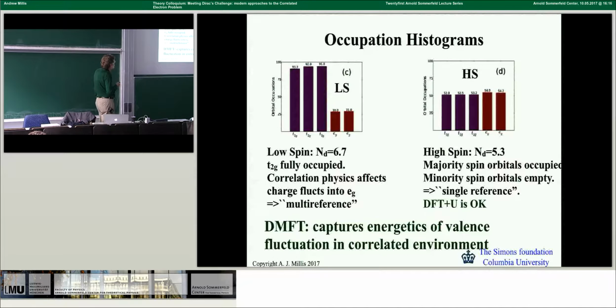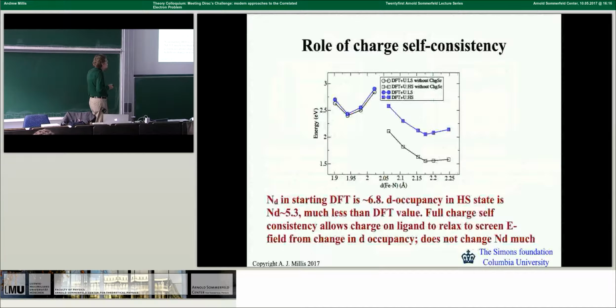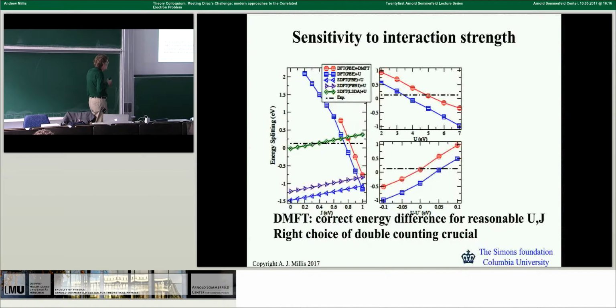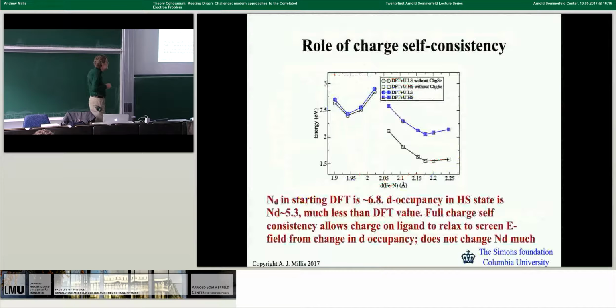In the low spin state, you have a rather different occupancy. In particular, you have two of the states which are partially occupied, but affected by correlation physics. So it's this thing which dynamical mean field theory is doing for you that the other methods don't. It's capturing correctly the energetics of valence fluctuations in this correlated environment. You also can talk about charge self-consistency, which is important. Now, so this is what's good.